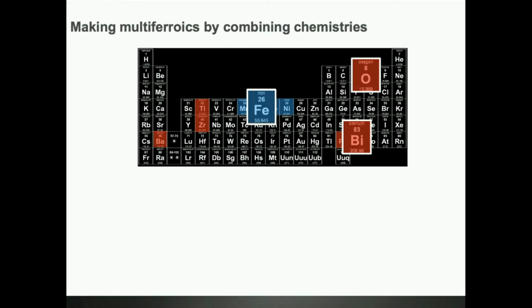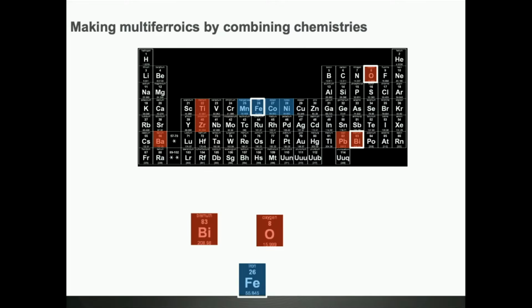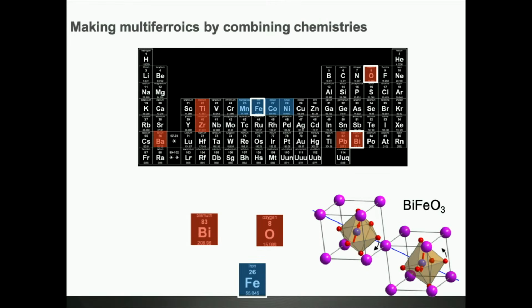And the simplest one was basically just by combining the chemistries, by making compounds that contained both the atoms that are good at being magnetic and the atoms that are good at being ferroelectric, at making electric dipoles. And here the prototype is bismuth ferrite, bismuth iron oxide, which is a perovskite structure in which the magnetism comes from the iron, from the fact that the iron has a very large magnetic dipole moment. And the ferroelectricity in this case comes from the bismuth, which is good at making an electric dipole because it has a lone pair of electrons that can make an electric dipole. So this was our first route to making a really good multiferroic.